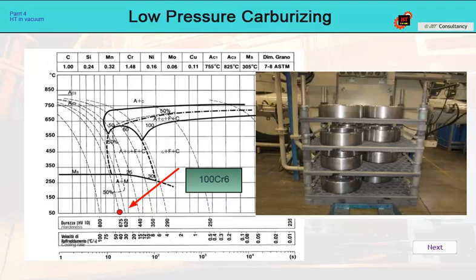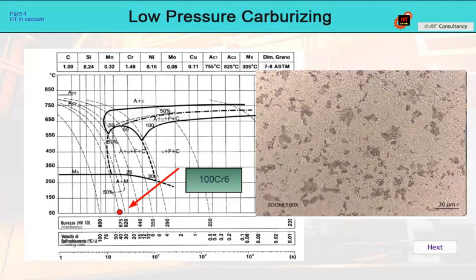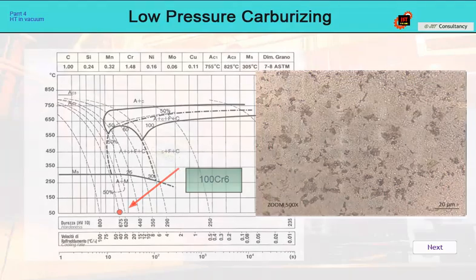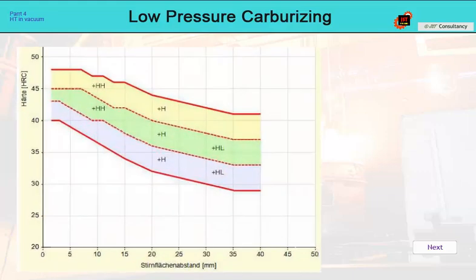In terms of hardness, the parts hardened in 20 bar nitrogen were perfect. However, the structure was flawed because there are inadmissible phases of troostite. This is not visible at first glance. The cooling rate was therefore just at the limit of possibilities, but the presence of troostite was the impulse to exclude nitrogen from the considered variants.